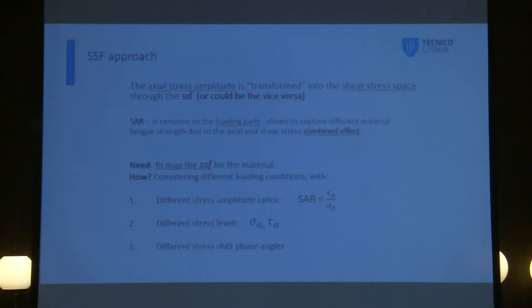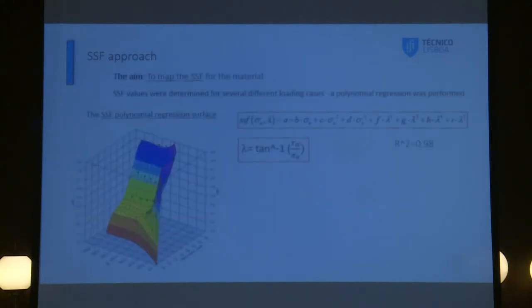The stress amplitude ratio is sensitive to the loading path. What we are seeing here is that we should take into account the combined effect of the shear and the axial stress. What we need to do is we need to map the SSF, this coefficient. And how can we do that? We have managed many, many tests, because we need to take into account different stress amplitudes, different stress levels, and also different phase shift angles. As you can see, we can combine and we can attain many, many different state conditions. We have performed a lot of tests.